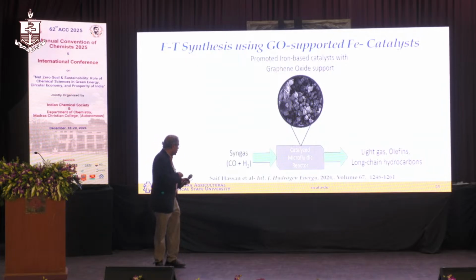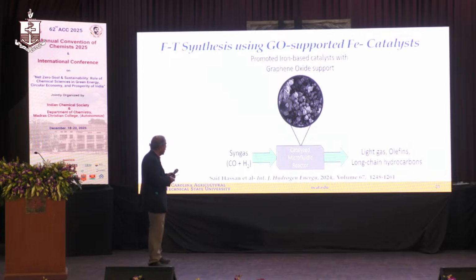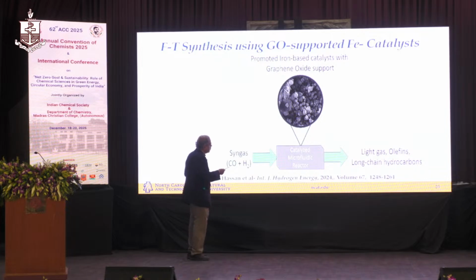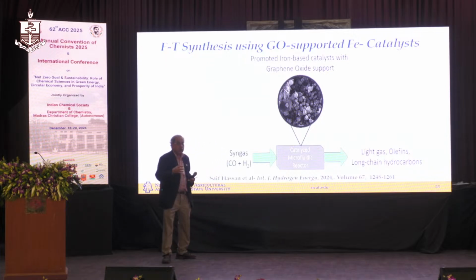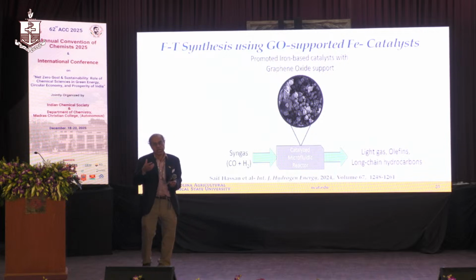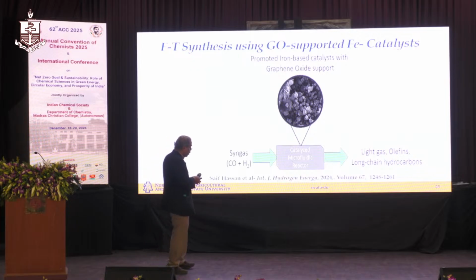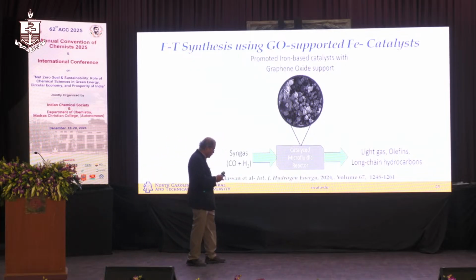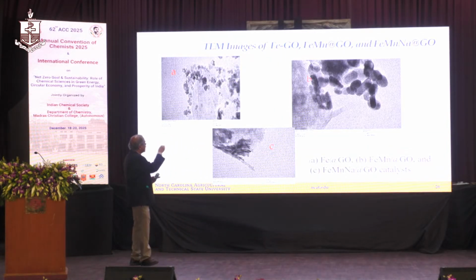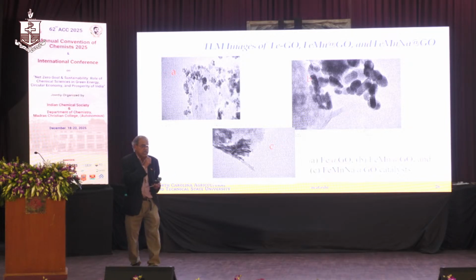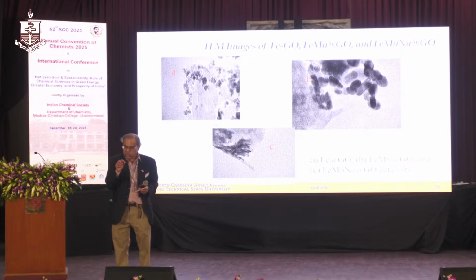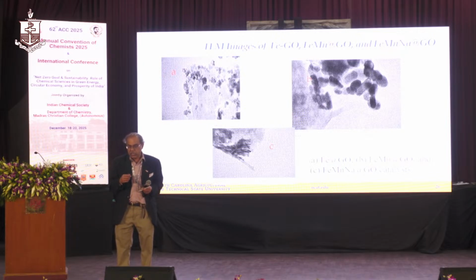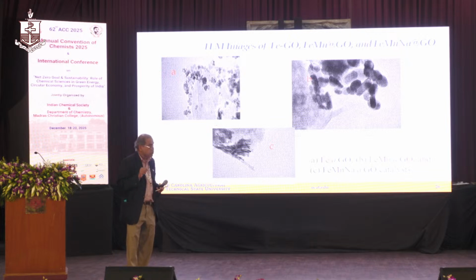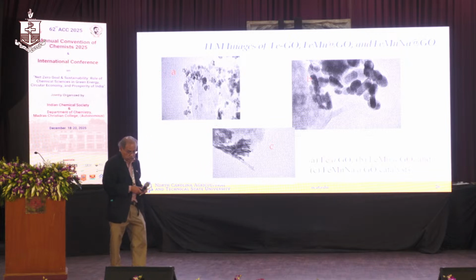So this is one of my undergraduates, Saif Hassan. He actually started with this project, with my postdocs and the PhD students, and we wanted to see what will happen if you use graphene oxide instead of silica, alumina, all that I told you, right? And so our goal is really to make these olefins and the long chain hydrocarbons. And you see, this is how the catalyst looks. What I'm trying to show you here is graphene oxide and the iron as the catalyst. Then we use a promoter. What is a promoter? It just promotes, like manganese and sodium, these metals, which basically makes the basicity higher. And how that will have an effect on the conversion.